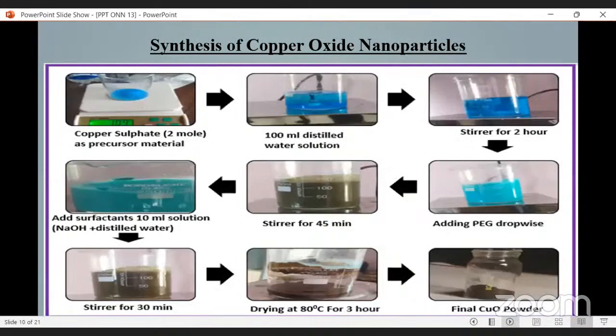Now this is the synthesis of the copper oxide nanoparticle which I have made. I have taken copper sulfate, 2 mole, as precursor material. Then I mixed it in 100 ml distilled water solution and stirred for 2 hours. Then I added PEG, that means polyethylene glycol, dropwise, and then stirred again for 45 minutes. Then I added 10 ml surfactant solution which contains sodium hydroxide and distilled water. Again I stirred for 30 minutes, and after that I dried it at 80 degrees centigrade in a furnace for 3 hours. Then after grinding, I obtained the final copper oxide.